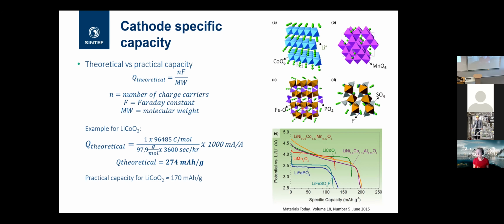Oh, and one thing I forgot to mention here, which I wanted to say something about. You will see in some of these figures, for instance, the lithium iron phosphate, the blue line, that it has a quite flat plateau. Whereas if you look at, for instance, this orange line, the NMC material, it has a much more sloping shape. The reason for that is that you have different mechanisms for the discharge. When you have this sloping shape, that means that you form a solid solution. The lithium forms a solid solution with its host structure. Whereas if you have a flat plateau like this, it means that you have a first order phase transition. So it's slightly different mechanisms for the insertion and deinsertion of the lithium ions.